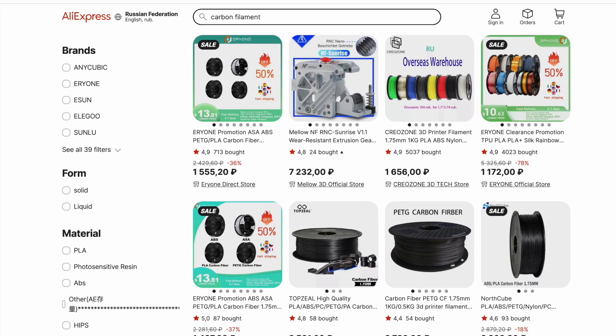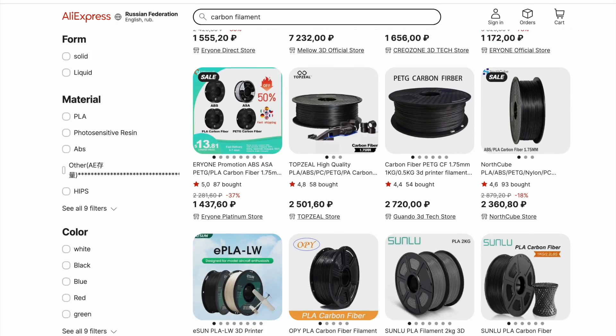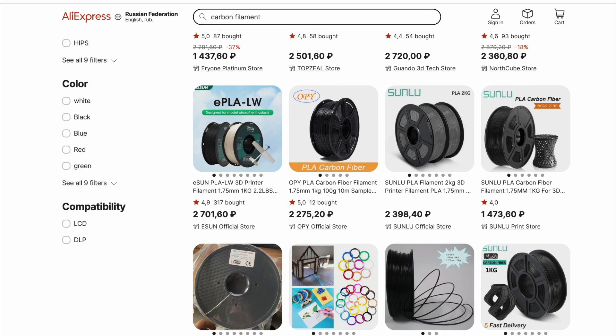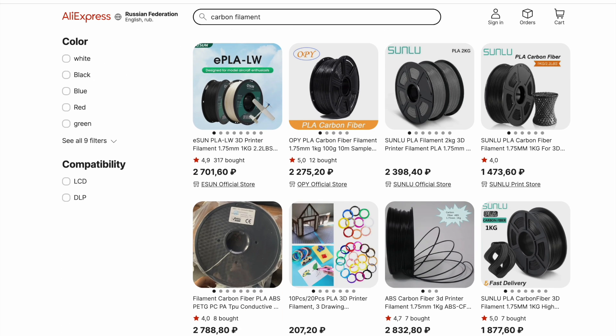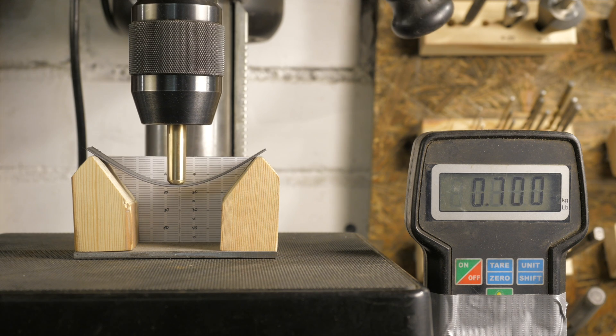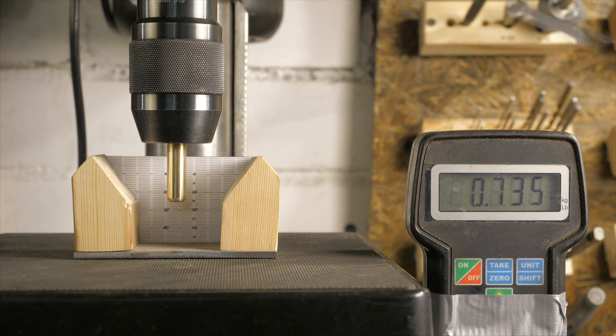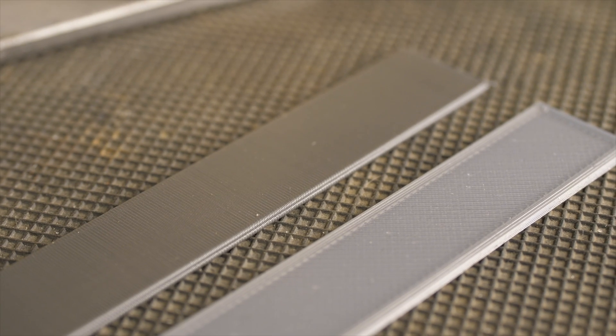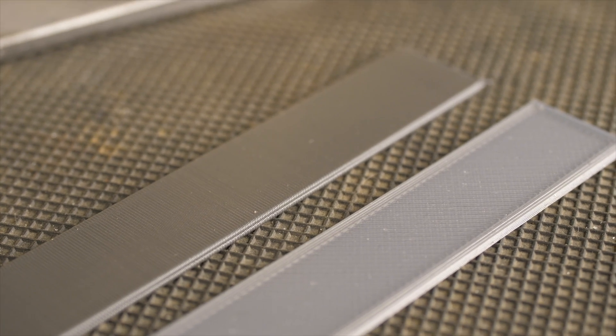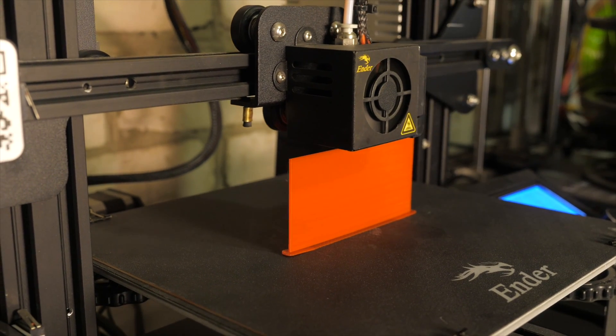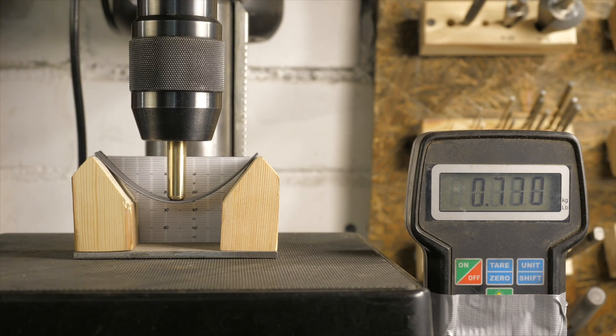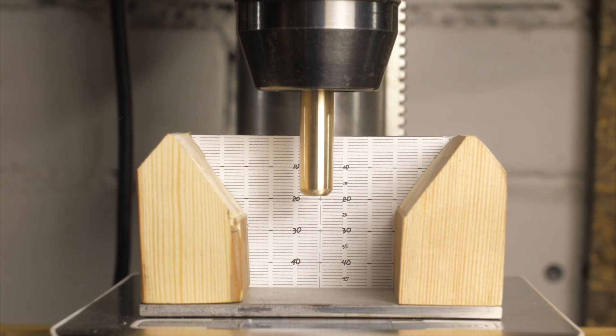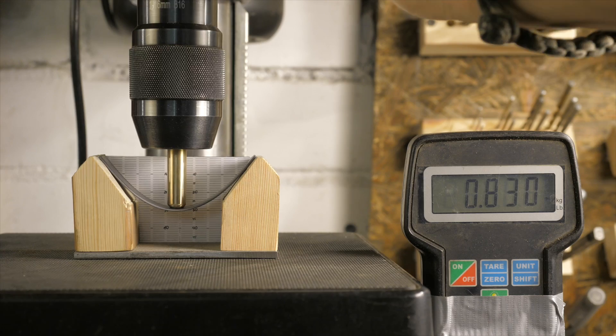Stronger and more expensive materials with the addition of carbon fibers allow for a slight increase in detail along the print lines, but do not allow to achieve the required fracture strength. When using any material, the part printed using FDM technology will in any case break between layers, even after a slight load.